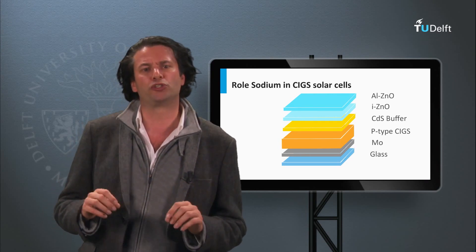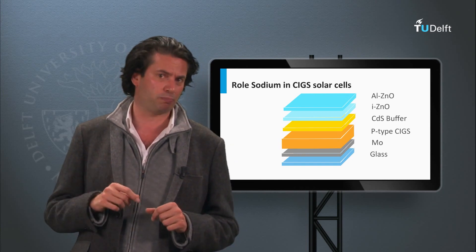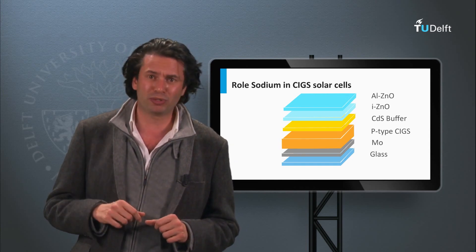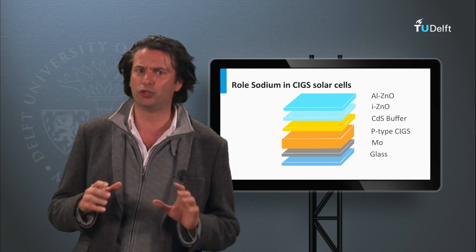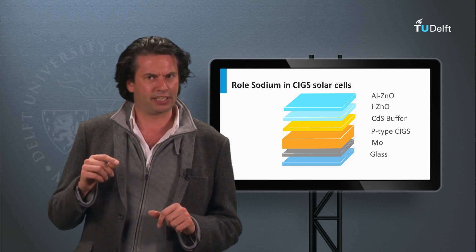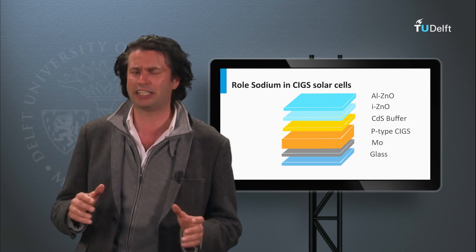Typical optimum concentration of sodium in the CIGS layers is 0.1%. The sodium source in the growth mechanism can be the soda-lime glass used as substrate.